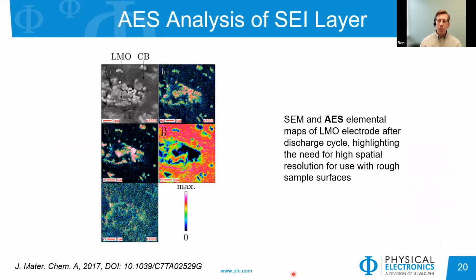With a similar technique, Auger analysis, again using our high spatial resolution, we can look at these SEI type layers. What we're seeing here is a lithium manganate type material with carbon black. And after cycling, we can see some different features around the borders of the manganate material. The scale bar here is about 2 microns. Using the high spatial resolution, we can map out where those features are after we cycle.